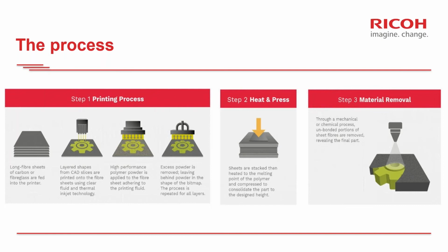So the first step, the printing process, involves feeding a set of long fiber carbon or glass fiber sheets into the printer. They are then used effectively as a print bed. A clear binding fluid is then jetted onto the sheets using an inkjet head, and the polymer powder is deposited on top. This then adheres to the printing fluid and fibers underneath. The excess powder is then vacuumed off, recycled into the machine, and a powder coated layer is left behind. The process is then repeated for all subsequent layers.